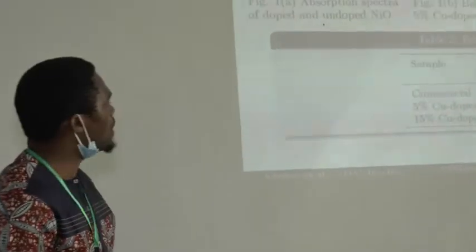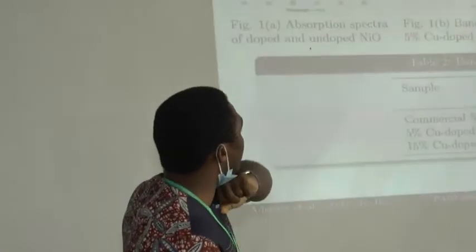Then this is the characterization, result and discussion. Figure A shows the absorption spectrum of doped and undoped nickel oxide in comparison with the standard nickel oxide nanoparticle. Figure B shows the band gap plots of the 5% copper doped nickel oxide nanoparticles, while figure C shows that of 15% copper doped nickel oxide nanocomposites. Now, the band gap summary. We have the commercial, which is the standard, the bench nickel oxide, the band gap was 3.94 eV, while that of 5% copper doped nickel oxide was 3.45. When the doping was increased to 15, it decreased to 3.25 eV.